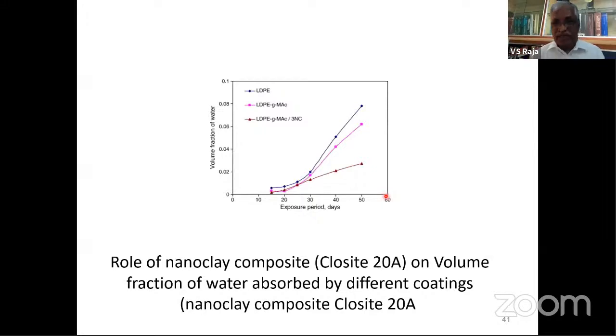A very interesting thing is that the kind of pigment that you add plays an important role. One of the distinguished panel members talked about nano, right? These nano pigments are very important. We just looked at the role of nano clay composite, Cloisite 20A, right? It's a clay actually. And when you add this clay, look at the water absorption. Look at this y-axis, volume of water absorption versus exposure days. This gives you the lowest amount of water absorption here. That is due to the addition of the clay, right? The clay addition reduces the water absorption and so improves the performance of the coatings.